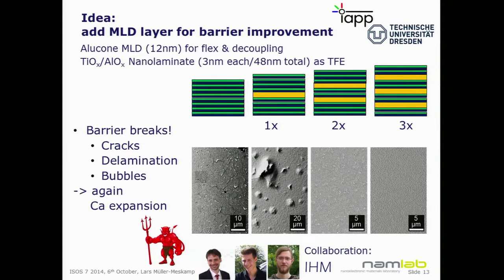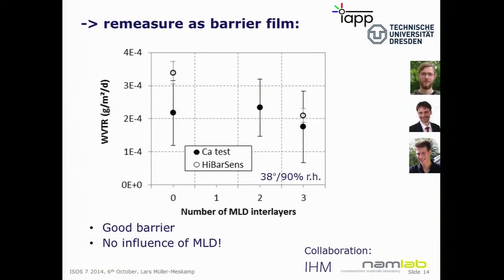What you also see is that for the 3 layers of MLD, it looks pretty fine. It's still there. So there's a good barrier here and a poor barrier there. So we wanted to know what's the real barrier of these stacks. So we went back to our original configuration, just put the barrier on top of a planarized PEN foil and the calcium test on top. And there you can see the number of MLD layers doesn't make a difference. So this is around 2 times 10 to the power of -4, regardless of the number of MLD layers.